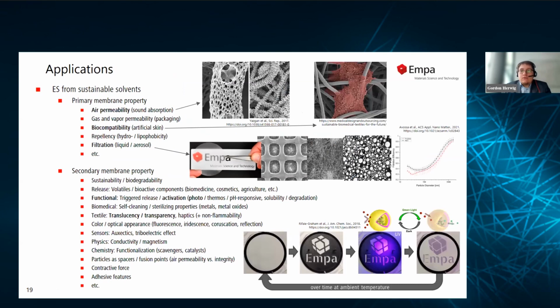So as a last overview, applications range from air permeability, gas and vapor permeability, biocompatibility, as cells really like this as a substrate, but aren't really growing through. So you're not having any issues with tissue ripping off when you remove it, or at least not much. Repellency and filtration, as we've seen here in the nice Hello Mask project from my colleague, where we've made a transparent mask. And this is basically all the primary membrane properties, but we also have secondary membrane properties that we can especially incorporate with blend or dispersion or emulsion electrospinning, or simply with green solvents.